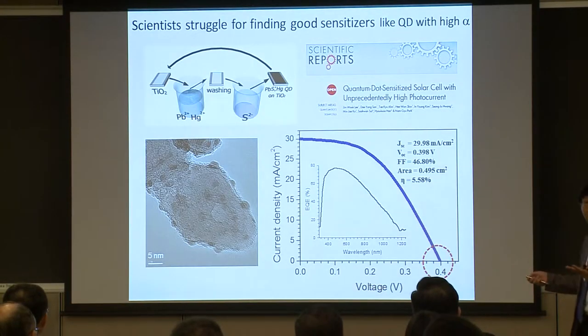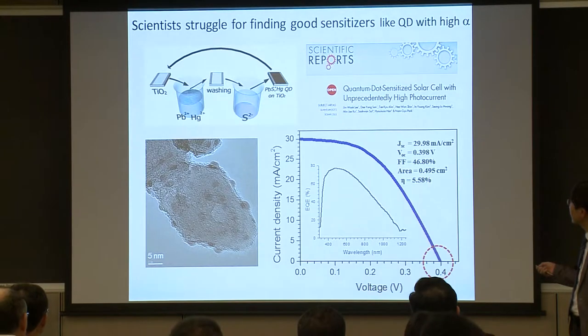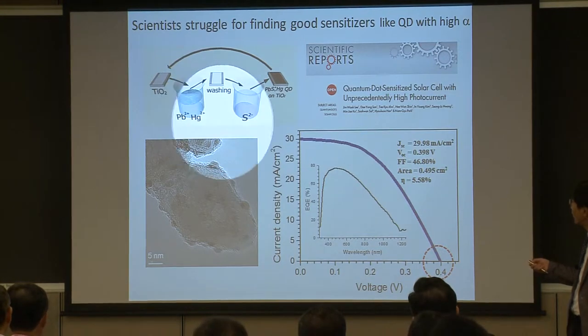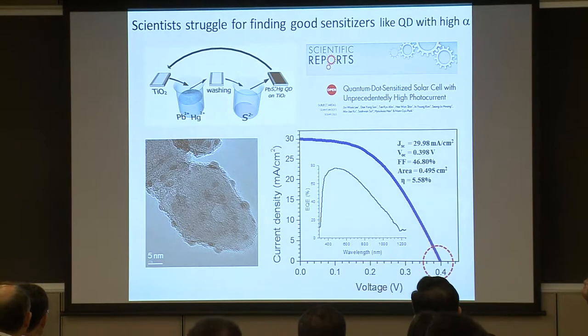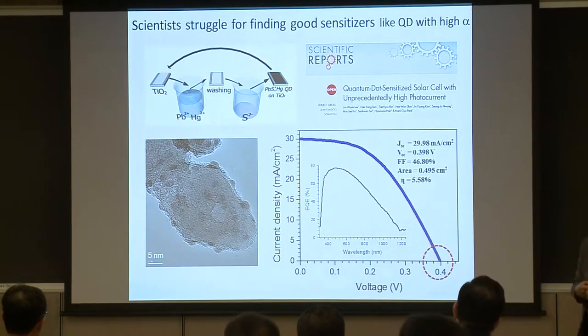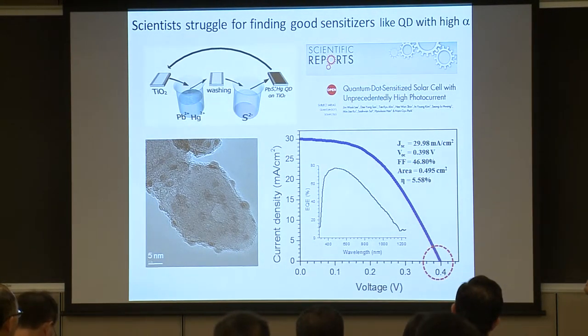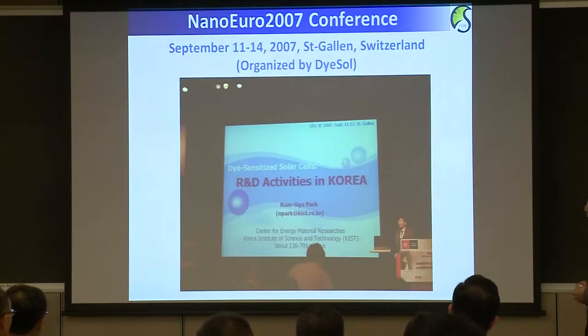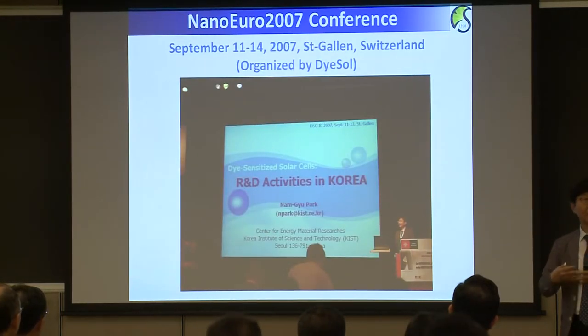So I was also involved in quantum dot sensitized solar cells. At that time we developed lead sulfide doped with mercury, and we achieved almost 30 milliamps per square centimeter, which was about 6% efficiency. So pretty high efficiency for a quantum dot sensitized solar cell. But you know, it suffers from very low open circuit voltage from this quantum dot because of high surface area, high surface state. So people would like to find a better sensitizer in dye-sensitized solar cells to improve efficiency further.